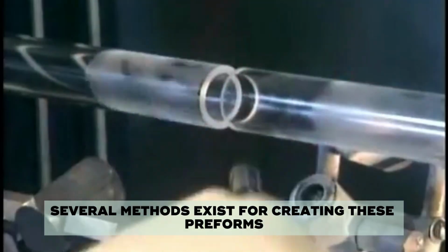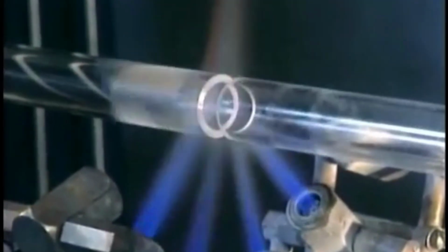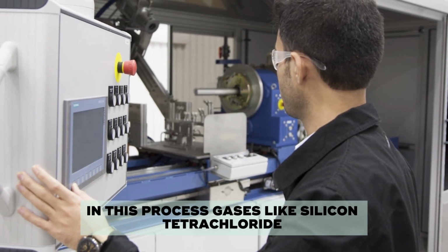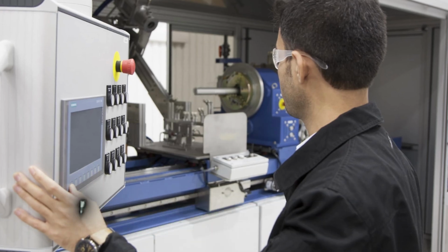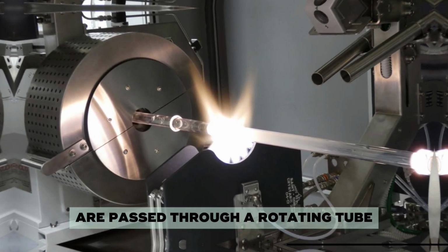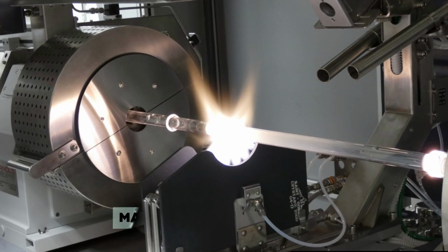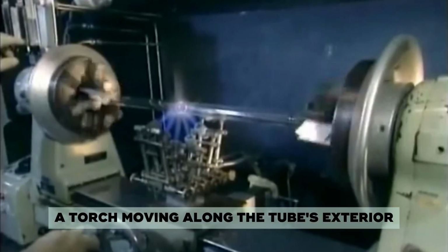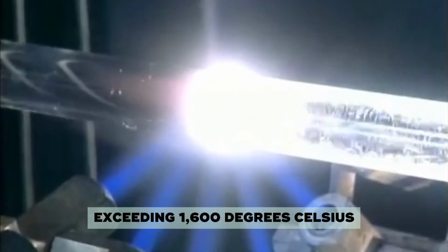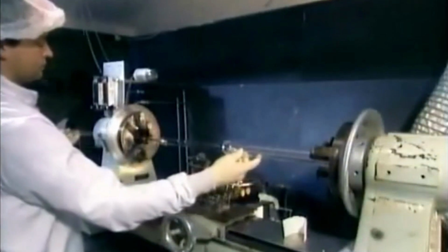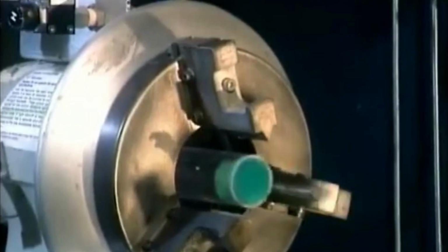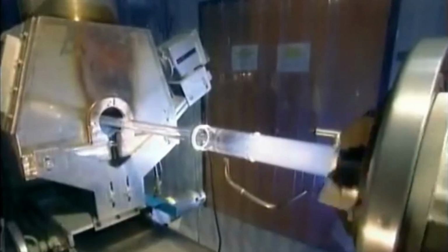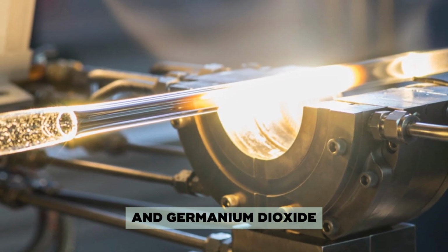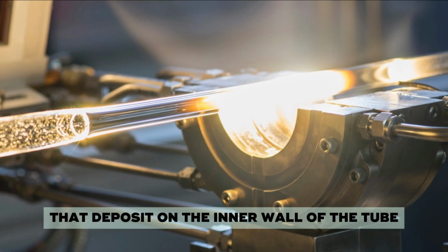Several methods exist for creating these preforms, but one of the most common is modified chemical vapor deposition, MCVD. In this process, gases like silicon tetrachloride and germanium tetrachloride are passed through a rotating tube made of synthetic quartz. A torch moving along the tube's exterior heats it to temperatures exceeding 1,600 degrees Celsius, reaching up to 1,800 degrees Celsius. At these extreme temperatures, the gases react to form fine particles of silica and germanium dioxide that deposit on the inner wall of the tube.